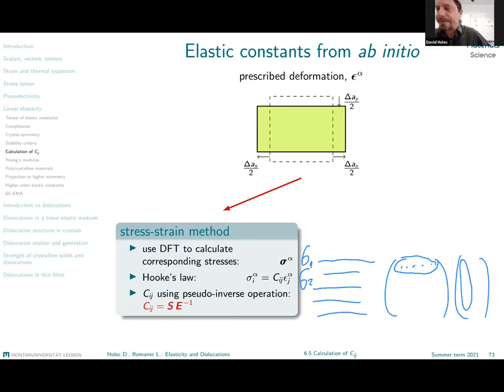with the strain tensor. Even if we apply the known relationship that the matrix of elastic constants is symmetrical with respect to the main diagonal, we still do not have enough equations to fully determine the components of this 6 by 6 matrix. Maybe we would have that in some special cases when we say we have a cubic material and therefore there are only 3 unknown values of this elastic constants matrix. Or if you say we have isotropic material and therefore there are only 2 unknown values. But in general case, we have too few equations to determine up to 21 independent components of the matrix of elastic constants. So what we have to do?